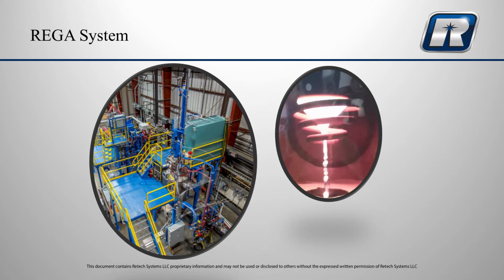Okay, so just a very simple picture of the REGA system shown on the left, the decking, and the melt chamber is actually quite small. Most of the system is actually the feeder mechanism for the electrode. These are about 1 meter long electrodes that are fed into the system, and actual melting and atomization conditions shown on the right. So you see how the dripping action of the induction coil melts the material.